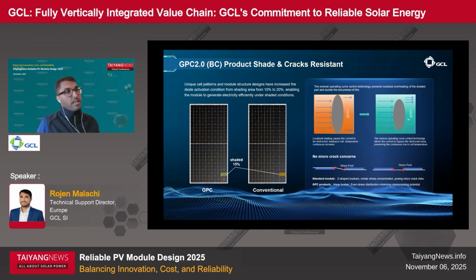Another reliability benefit is hotspot suppression. In conventional architectures, shading forces current through blocked cell areas, causing local overheating and accelerated aging, and in extreme cases, even fire risk. Our reverse current operating control technology avoids this by letting current bypass the shaded zone smoothly, preventing thermal spikes and protecting the cell architecture.